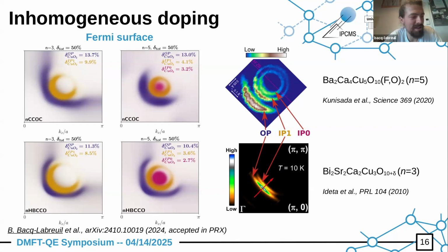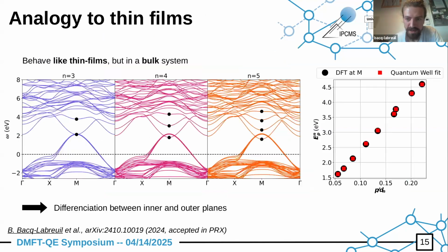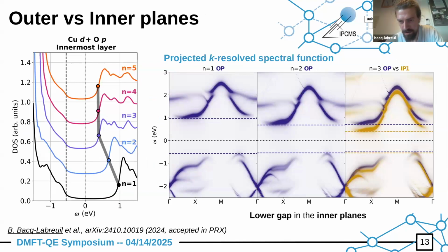So that's the funny part. It doesn't have to be in the antiferromagnetic regime to have signs of antiferromagnetism. I think we can see it more clearly here. If you look at the bottom part of these spectral functions, you can see between gamma and M, the dispersion basically is split into two small parts, and one has a dome shape between gamma and M roughly at the level of the dashed lines. But in technical terms, this is all 2x2 clusters, right? So this depends on the reconstruction, the momentum interpolation scheme you use. Yes, it depends a bit on it, but it's also robust. We have done a study in another work where we had 8-site clusters and larger clusters. This is really linked to this waterfall type of physics in cuprates.